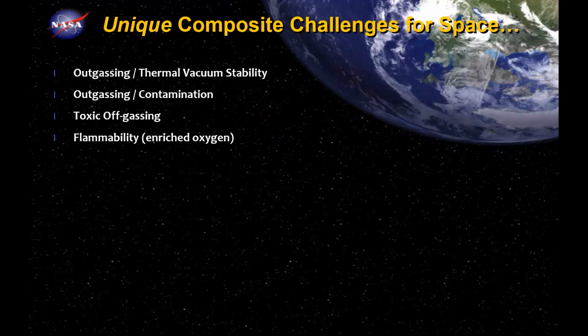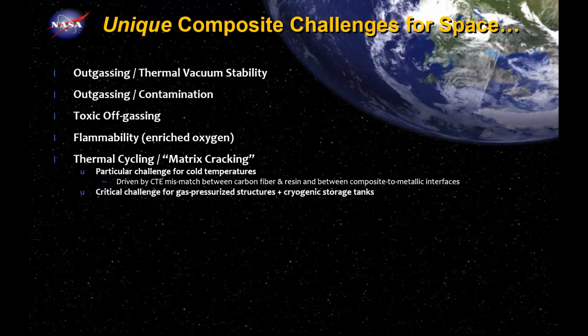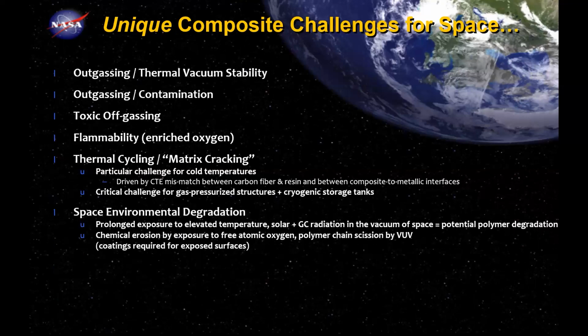Flammability turns out is a very big one for us as we think about going to the moon, because we want to push our oxygen levels upwards. The spacesuit operates at only about 3 psi of 100% oxygen. And it's critical that we have a pre-breathe environment that can be upwards of around 37% oxygen. Unfortunately, most all epoxy systems, polymer matrix epoxies, will readily burn in that kind of environment. So it's a pretty big evolving challenge for us.